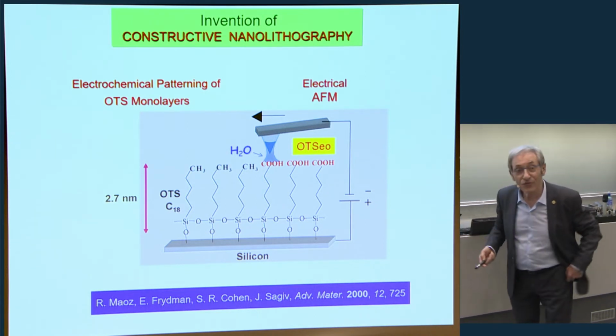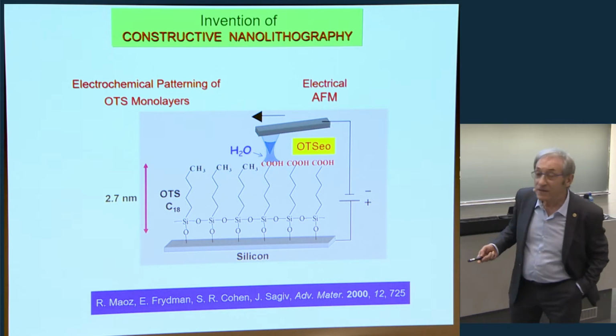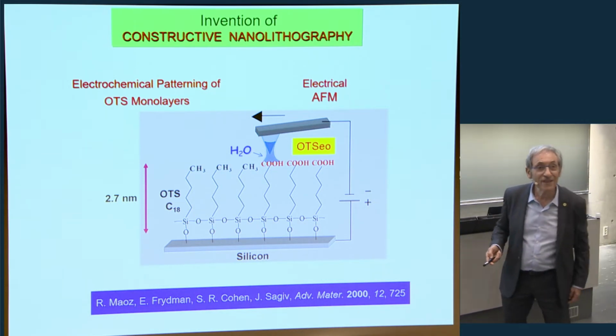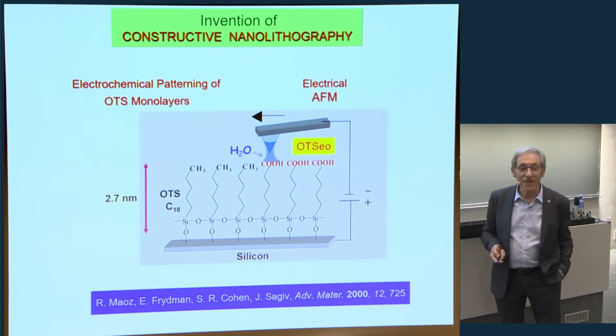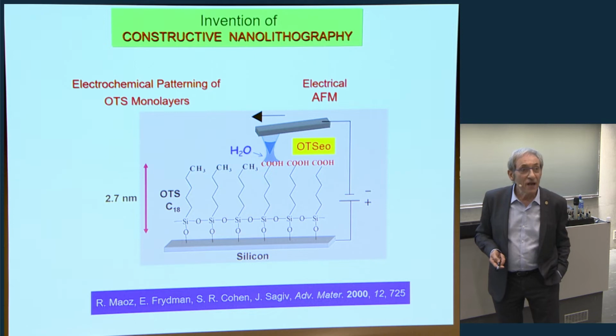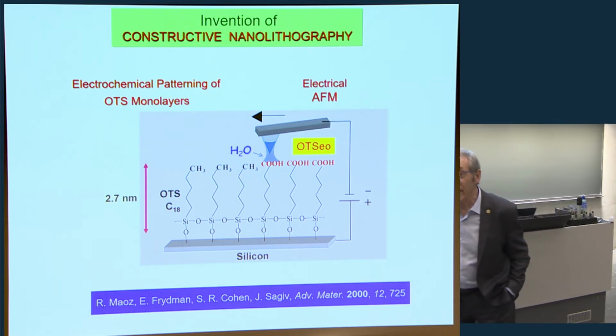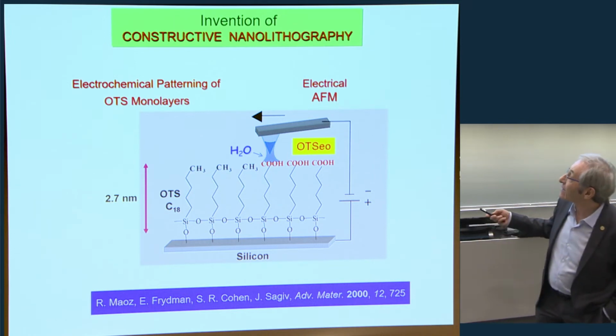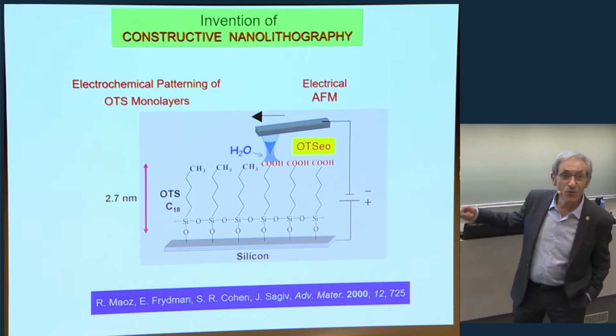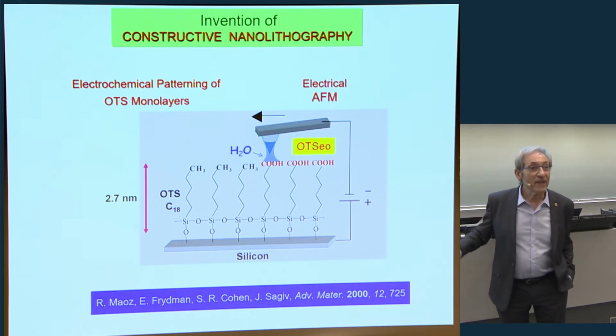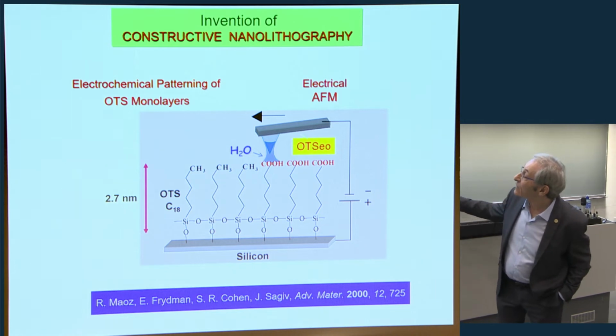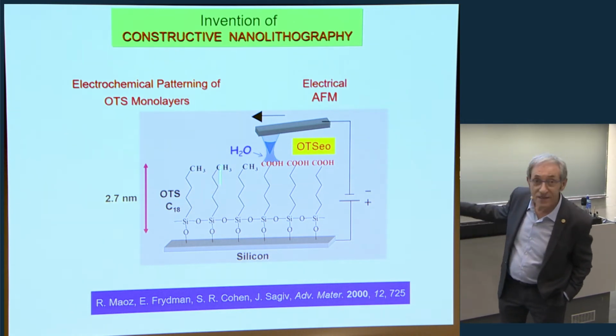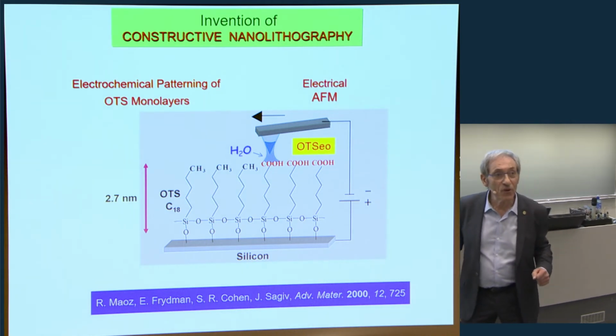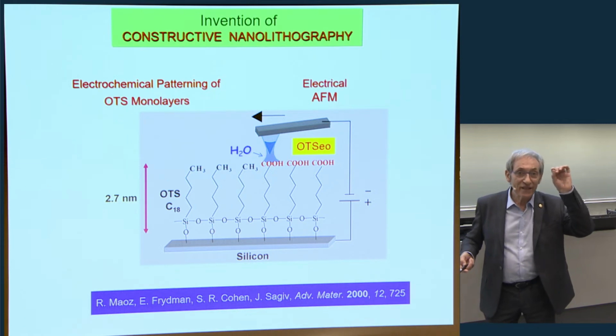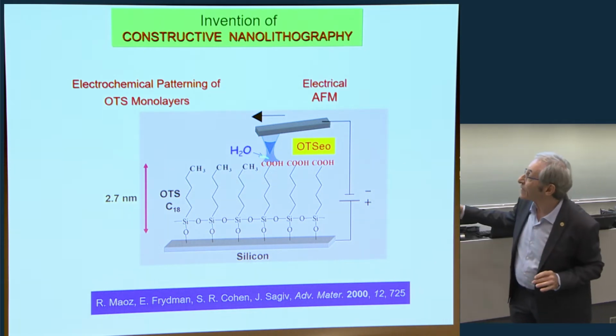Okay, so this is the invention of what we call constructive nanolithography. Again, Rivka, she's over there. She had the idea that we should be able to do something with this boring monolayer, with OTS. How can we functionalize its inert surface? When I started with the monolayer, it was long before the invention of the AFM, but in 2000, actually this work started in '98, the AFM was already available. And the idea was that if you take an AFM with a conductive tip and apply a bias, it should, this was Rivka's original idea, it should be possible, perhaps, to create a small spark in the air, and that will somehow affect the surface.